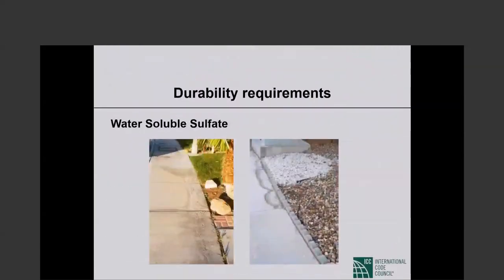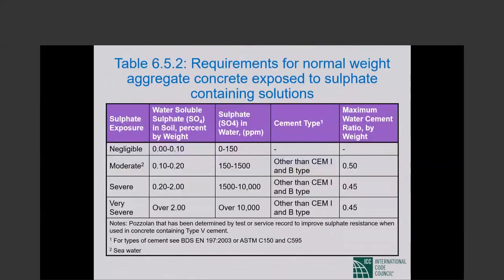We talked about water tightness, we talked about corrosion resistance, now sulfate resistance. So this is a BNBC table. The number is 652, requirements for normal weight aggregate concrete exposed to sulfate containing solutions. If the sulfate exposure is negligible, then there is no limitation on maximum water cement ratio. If the sulfate exposure is moderate, then the limitation is 0.5. If it is severe, it's 0.45. If it's very severe, it's 0.45.